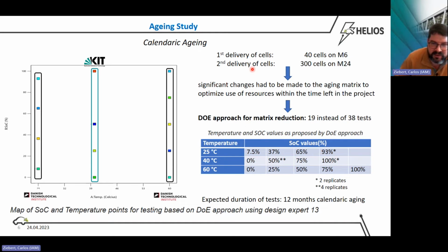In this case, we see that it was quite difficult to get cells from the manufacturer. So we got first cells from the manufacturer, 40 cells, where we could start some tests, but then it took until month 24 until we received enough cells to start the aging tests. So we had to make significant changes to the aging matrices to optimize also the use of the resources within the time left in the project.